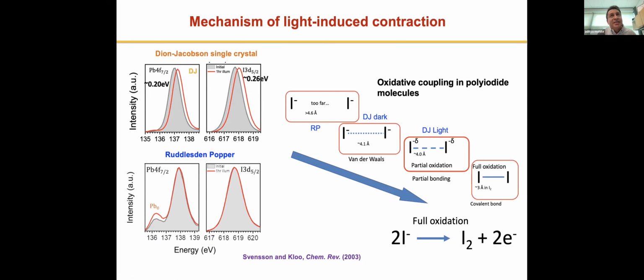And so we can actually understand this from the perspective of oxidative coupling in polyiodide molecules. So let me walk you through that. Here I'm showing you two iodine molecules, and when they are too far away, there is no real interaction. This would be very similar to the case where you have a Ruddlesden-Popper phase. These iodides don't really interact. Now, in the dark case, you have these Dion-Jacobson phases, and you can see about 4.16 angstrom there, which is about the van der Waals gap. And again, under dark, you have very little interaction.